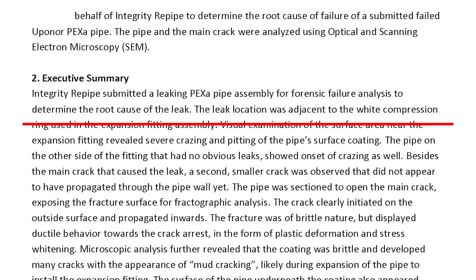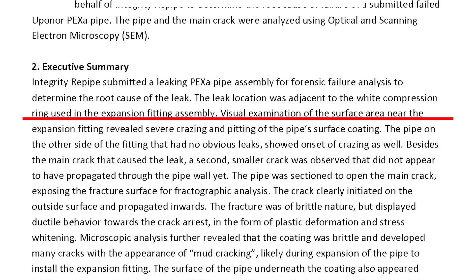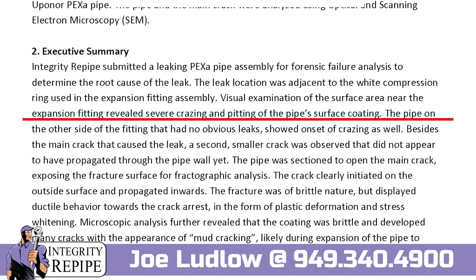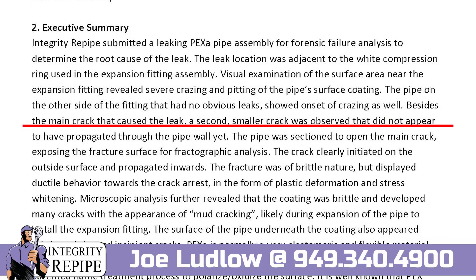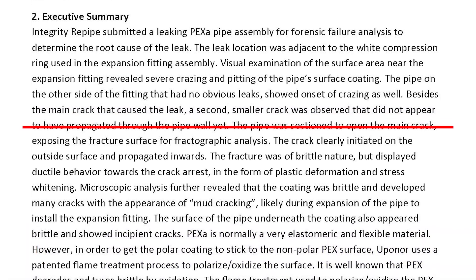The leak location was adjacent to the white compression ring used in the expansion fitting assembly. Visual examination of the surface area near the expansion fitting revealed severe crazing and pitting of the pipe surface coating. The pipe on the other side of the fitting, which had no obvious leaks, also showed the onset of crazing.